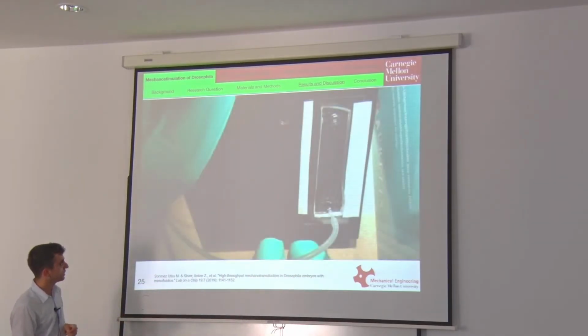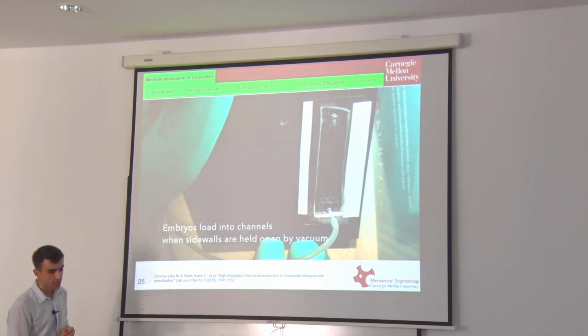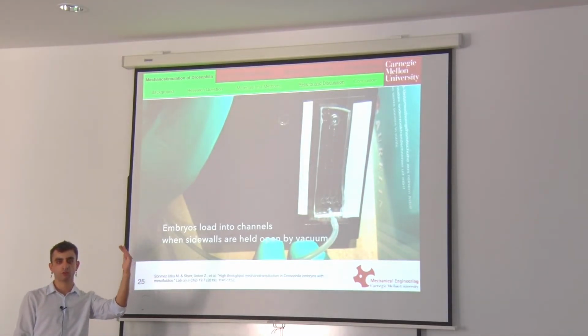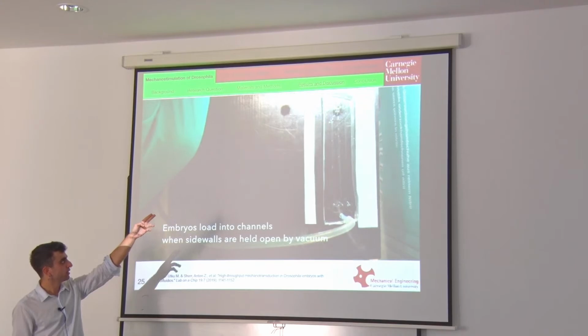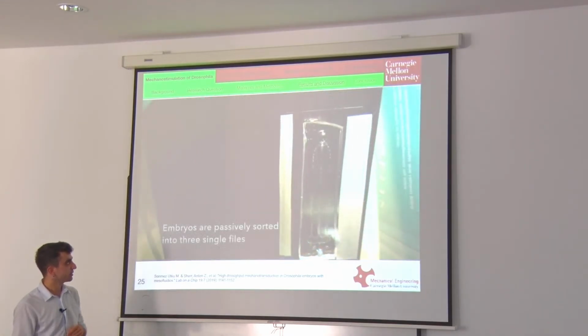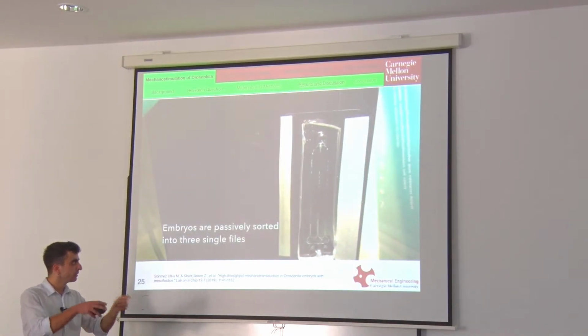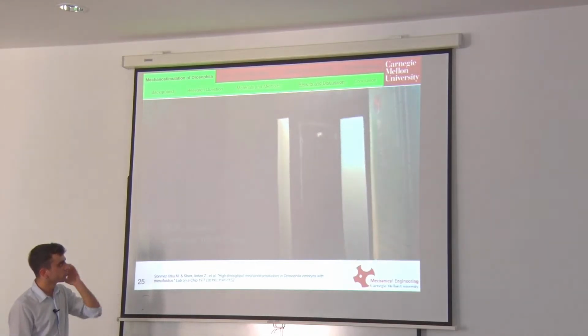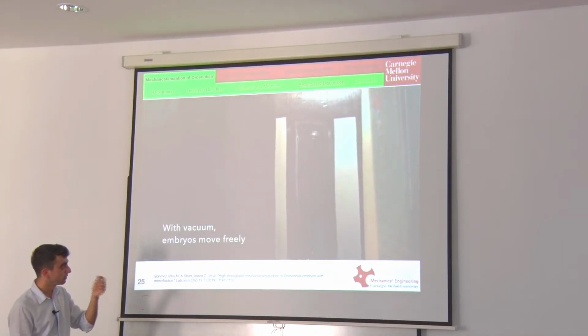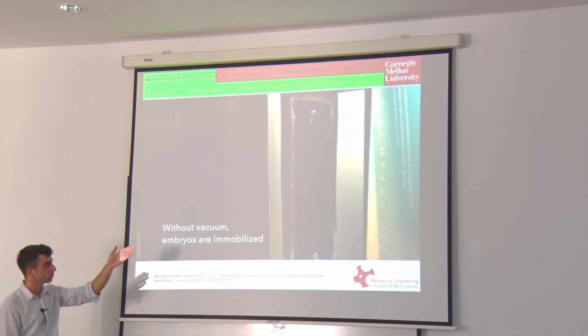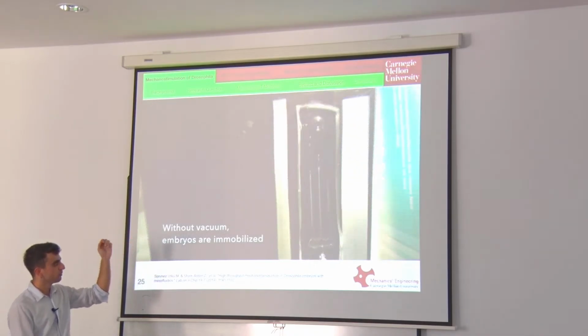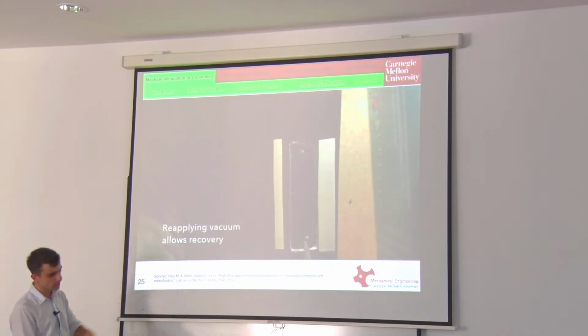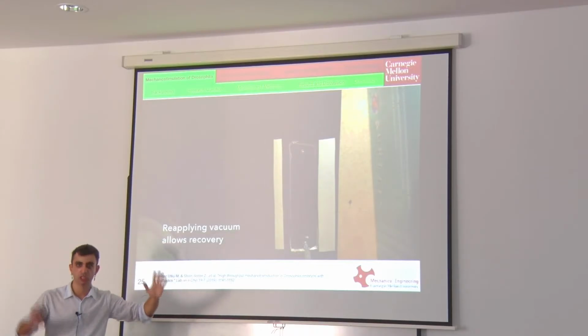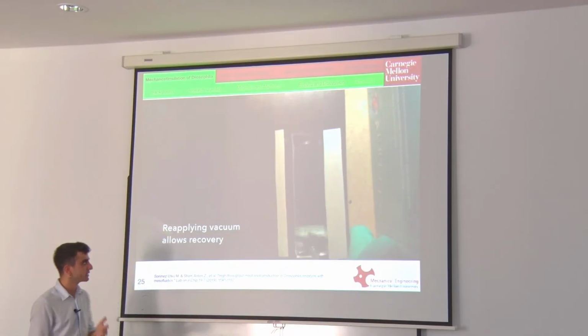And I can easily load these embryos inside these channels by just tilting the microfluidic channel after introducing the fruit fly embryos to its inlet. And by just tilting a little bit, in a couple of minutes, I can introduce hundreds of embryos. And under vacuum, they are moving freely. If I remove the vacuum, they are immobilized. And if I apply positive pressure, the walls deflect inwards and compress the embryos.